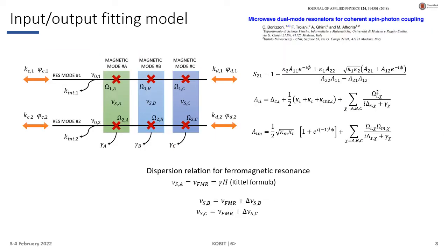We fitted the experimental data using an input-output model, which has been previously developed by the group of Professor Affronte for the dual-mode resonator with multiple spin modes. The model involves two different photonic modes, which are shown as horizontal lines, coupled to up to 3 magnetic modes, and each of them can couple to both resonant modes through its corresponding coupling rates, and all modes are characterized by their frequencies and the coupling rates.